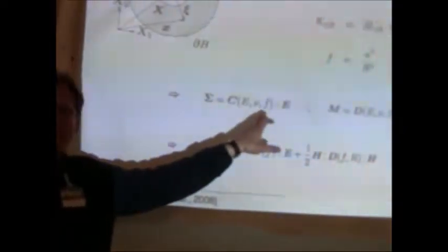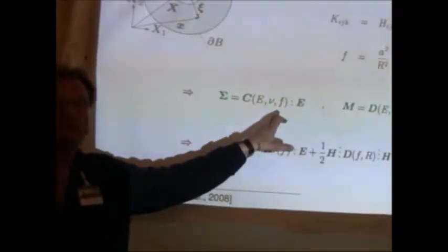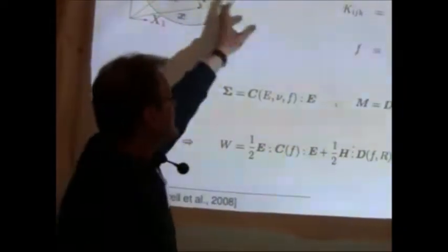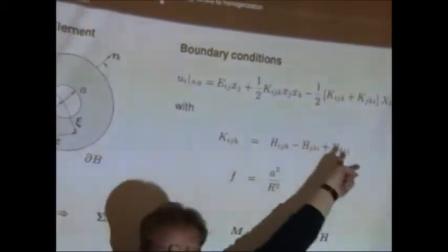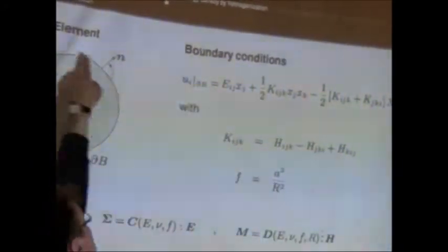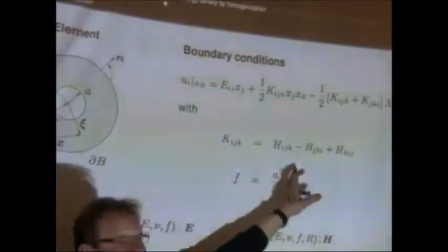Now the idea, which is actually from this work from Gologanu and Leblond, was that this only gives Cauchy continua, which means we can relate it to a microstructure, but only by densities, only by specific values. And they came up with the idea to say, no good, we don't prescribe a linear displacement field at the boundary, but a quadratic one, and we relate the coefficients of this polynomial at the boundary with the strain gradients.